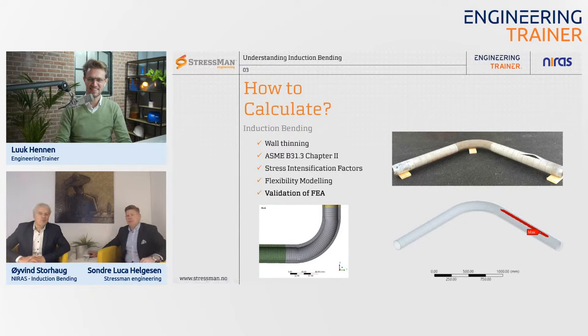They bent it, and all the wall thickness was measured along the mother pipe or the line pipe here. They bent it, which then we could confirm the formulas that we are using, as well as we got an accurate 3D model. It's not so interesting to watch because it looks like a perfect pipe, but it's actually not. So we modeled all the different wall thicknesses that were measured throughout here. So it should be as perfect a representation as possible. Nothing is perfect, but as close as possible.